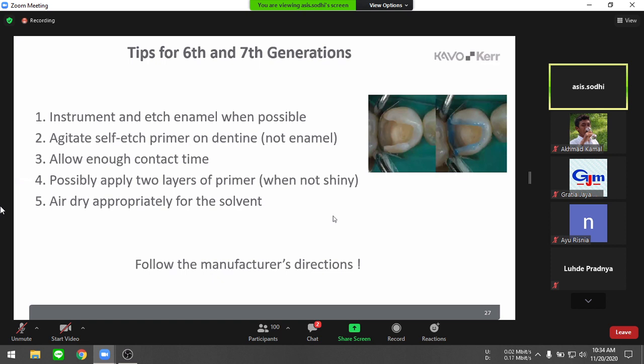So the key takeaway from here is that you can instrument and etch the enamel wherever it is possible. So you're using phosphoric acid only on the enamel surface. You're not using it all over the tooth surface. And this technique is called a selective etch technique, where you're using self-etch on the dentine, however, phosphoric acid on the enamel surface for increased bond strength.